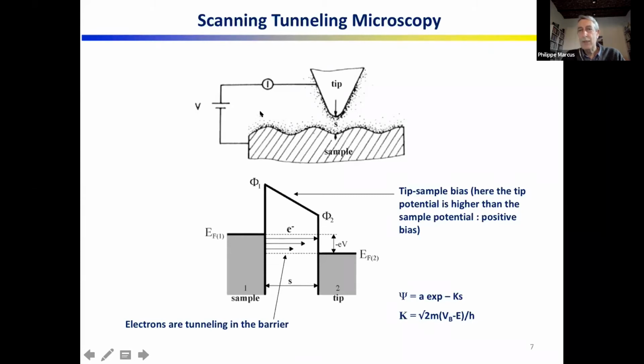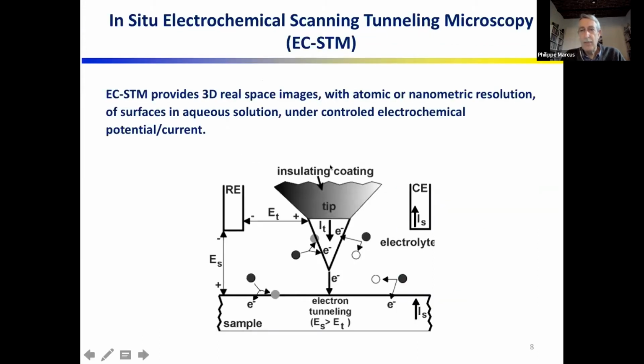And then we scan the tip along the surface. So we measure maxima in the tunneling current, which correspond to the position of atoms. So we can get an image of the topography of the surface with atomic resolution. And of course, we can also get an image with lower resolution. But atomic resolution is currently obtained. And this can be done in vacuum, in gas, or in a liquid.